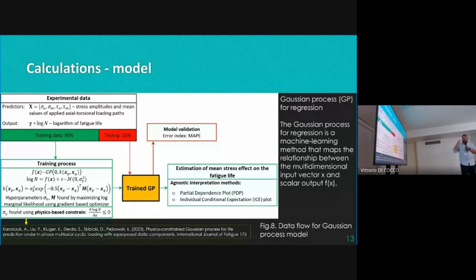Only during the training, I mean, actually standard procedures were used, but we had one physics-based constraint. It was that when the stress amplitude lowers, the fatigue life should be higher. This is standard, as it should be on the SN curve, right? And we used error index validation for the training data. Maybe it's also a standard one.